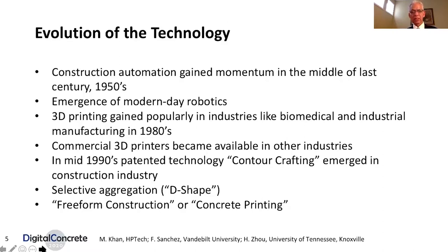In the mid-1990s, a technology called contour crafting emerged, which was later patented. This is an extrusion-based method and somewhat similar to shotcreting. The difference is that the extrusion in contour crafting is a piston pump mechanism like a syringe rather than a spray at high exit velocity as in shotcreting.